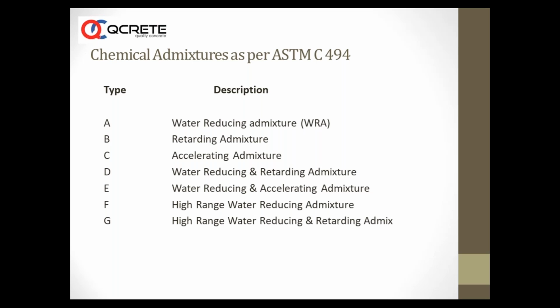Type F is where the shift has happened. You can say a paradigm shift has happened in terms of usage of chemical admixture, where people started using this kind of chemical admixture for all grades of concrete, where the dosage can be from 0.3 to 1.5 percentage, where you can use from M10 to M50. So here they are also called high range water reducing admixture.